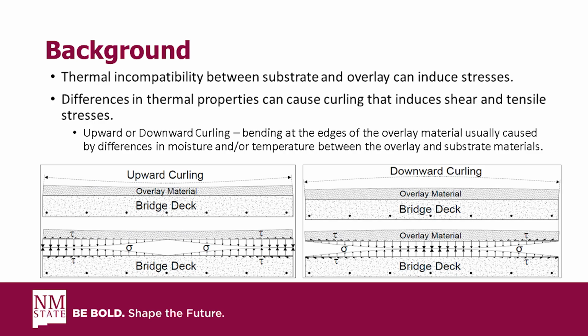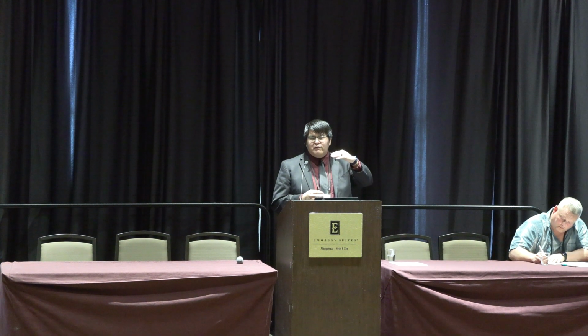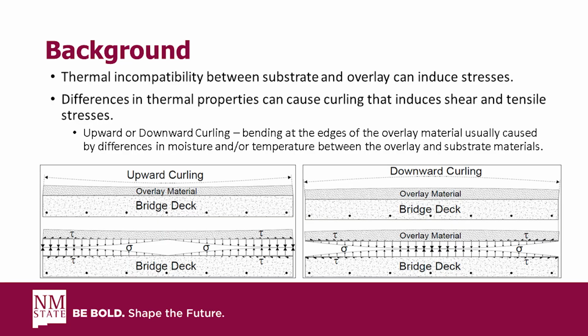and the differences in the thermal properties can provide this phenomenon called curling, where we have either upward curling or downward curling. Curling is essentially a difference in moisture above the overlay and below the overlay. So it can be either temperature difference or moisture difference. The worst case scenario would be upward curling, where we get maximum shear stresses at the edges and maximum tensile stresses at the edges.